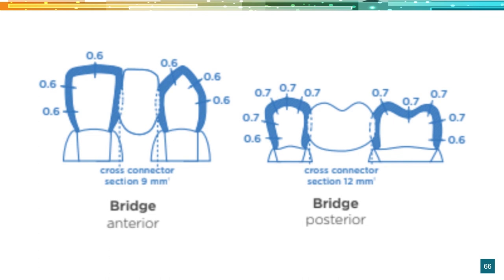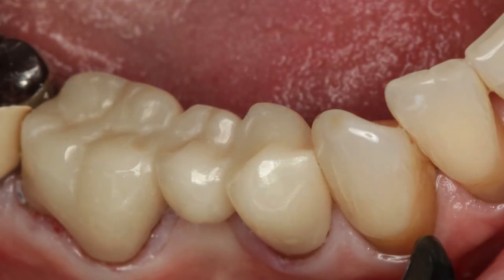Here's the biocopy — you can see it stitches together really well. I try not to add a lot of anatomy back into it, because if she's already ground off the anatomy or her bite just doesn't like it, I want to respect how her bite was before. The biocopy was dead on with zirconia, and I didn't have to reduce much more with that 0.6 mm thickness. She'll be ready for an implant someday, but for now her partial snapped right down. Another great purpose for zirconia is bridges — both anterior and posterior. Connector size can be a bit smaller: anteriors need a 9 mm² connector, posteriors a 12 mm² connector.